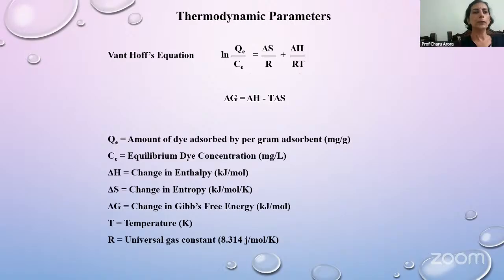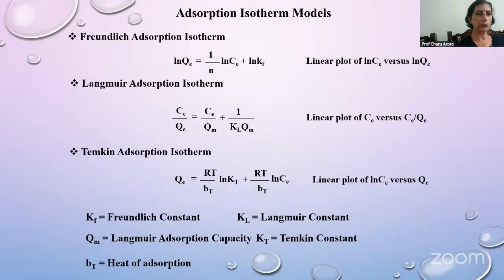We can also calculate thermodynamic parameters using this van't Hoff equation. The meanings of all the symbols have been given in this slide. Then we can find out the adsorption isotherm model using these equations. You all are familiar with Freundlich and Langmuir adsorption isotherms. For this, we plot log Ce versus log qe, and for Langmuir adsorption isotherm, we plot Ce versus Ce upon qe. Similarly, for Temkin adsorption isotherm, we plot a linear graph between log Ce versus qe.